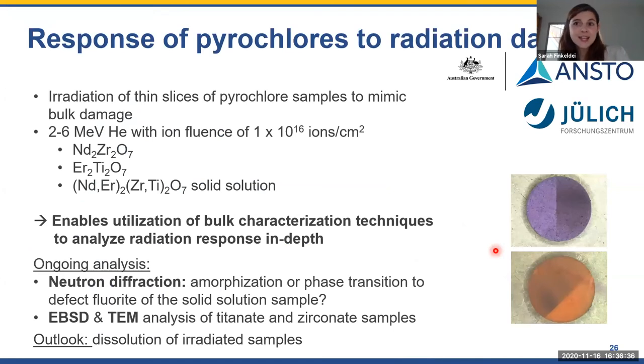Okay, and the last study that's currently ongoing, in collaboration with the Australian Nuclear Science and Technology Organisation, is the irradiation of some of those specimens. So we do this for a zirconate sample and for a titanate sample. The difference between zirconate and titanate pyrochlores is that titanate pyrochlores are actually known to undergo an amorphization when they get exposed to radiation.